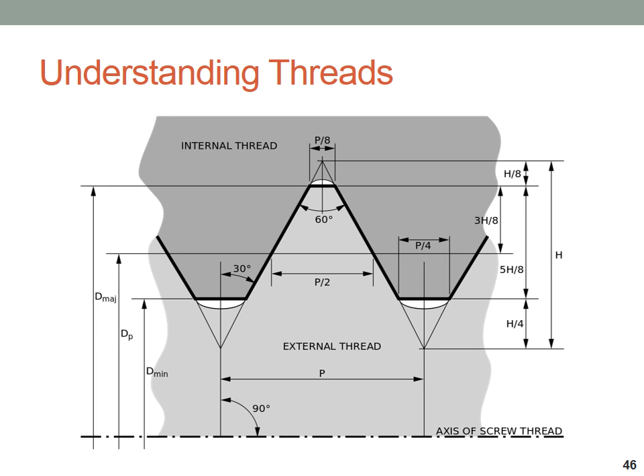And back to this drawing that I had, in this particular case, the pitch diameter, again, is the center line. If you took an equal distance between the theoretic top and bottom of that 60-degree angle, the pitch diameter is a line that travels through the center of that. In this case, though, you can see it's neither the center of the external thread nor the center of the internal thread. It's actually just the center of the theoretical center, I should say, of those.